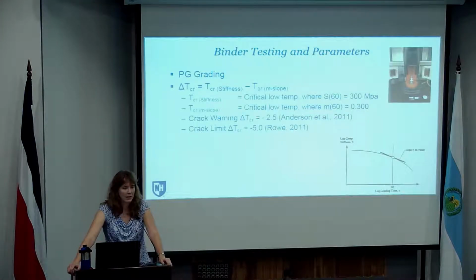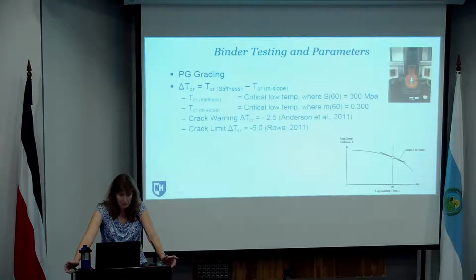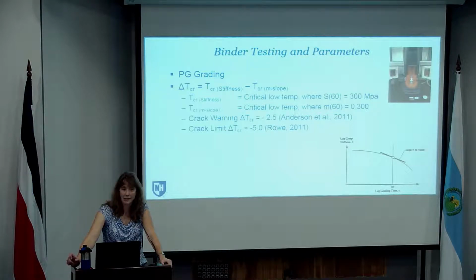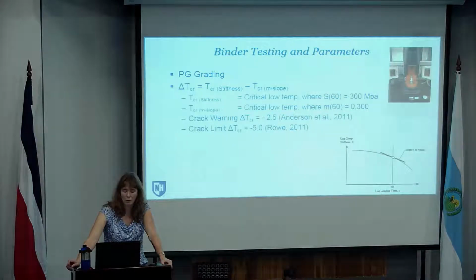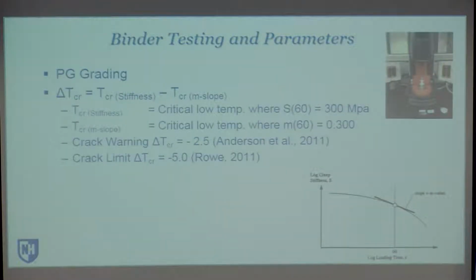A little bit more detail on the binder testing. PG grading, I think everybody's familiar with. The other parameter that we've been looking at for the binder side of things is the delta TCR value. So it's the difference in the temperature at which it meets the BBR stiffness criteria of 300 megapascal and the temperature at which the material meets the low temperature slope, or m-value, which is 0.3.